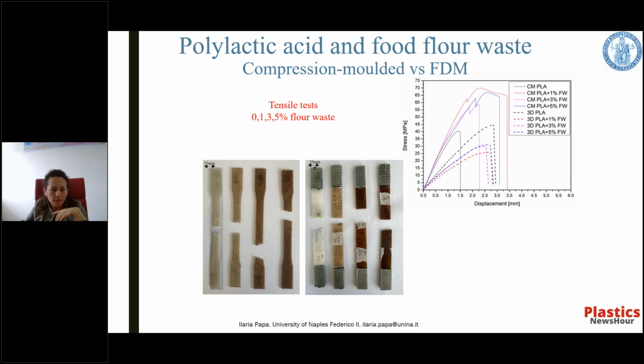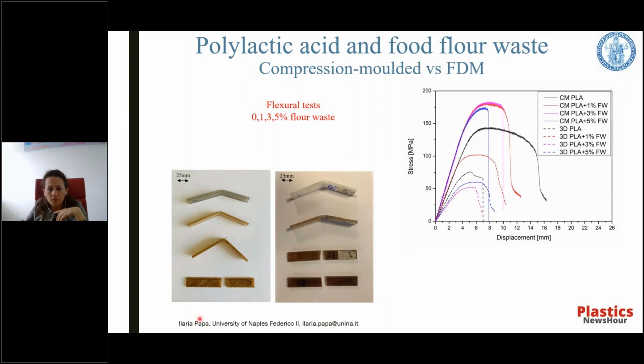So I have shown you 3-point bending test results, and even if in this case the compression molded samples with the same filler weight content show higher maximum load and modulus values than those obtained by FDM, thanks to the better compaction. In particular, for the compression molded parts, a higher value of the maximum bending load is recorded with respect to the reference neat matrix, the black line,